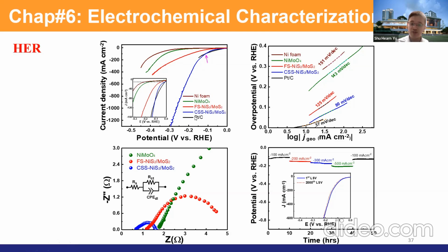However, our sample, CSS, controlled surface sulfurization, nickel sulfide and molybdenum sulfide, has very good performance at high current density. As compared to the fully sulfurized nickel sulfide and molybdenum sulfide, the performance is very mediocre. And we also found the Tafel slope here, and we performed the Nyquist plot. Everything I think you guys are very familiar with. And we also performed a stability test over 50 hours, and you can see that after 50 hours, the current can go back to here.